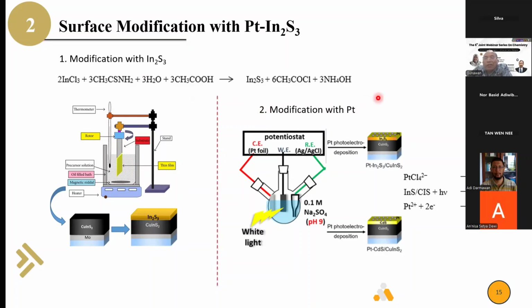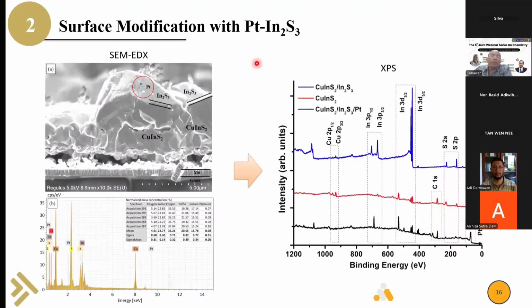And then after that, we deposit nanoparticles of platinum by using 0.1 sodium sulfate with illumination, so that nanoparticles of Pt will deposit on the indium sulfide. Then we can check by SEM and EDX whether indium and platinum are deposited or not. So we can see there is platinum on indium sulfide, and this one is copper indium sulfide, actually not more than 1 micron.